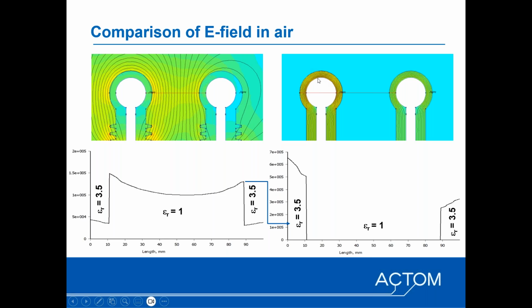The design of the electrode and the design of the epoxy around the electrode is controlled and can be done properly, so that you can control the magnitude of the appearing field stress, so that you don't exceed the dielectric breakdown strength of the epoxy.